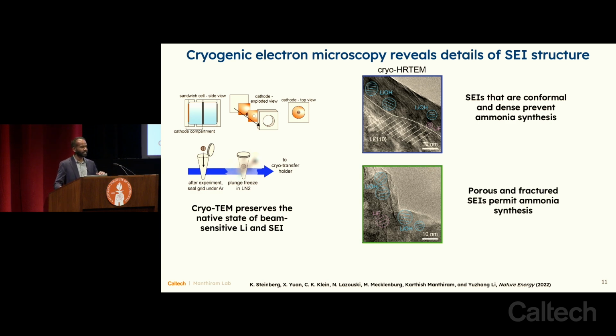And what we found is that if we take electrolytes that work well, that have high Faraday efficiencies, and then we take electrolytes that don't work well, that have low Faraday efficiencies, we could rather easily classify them into these two types of images: ones that are conformal and don't work well, or SEIs that are porous and fractured that allow for transport of nitrogen gas through them such that the reaction can happen. And so we now finally had a physical handle, something that we could see and believe, that could tell us why a certain solvent or certain proton donor works well and another doesn't. And this was really driven by an interdisciplinary advance, taking a tool from another field and bringing it here to catalysis to be able to understand something new.